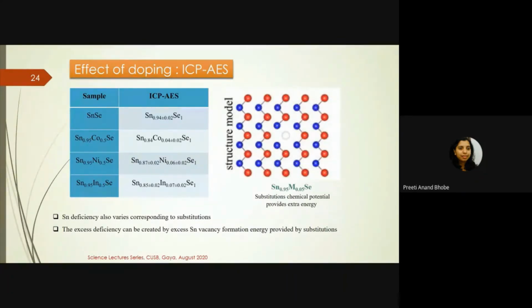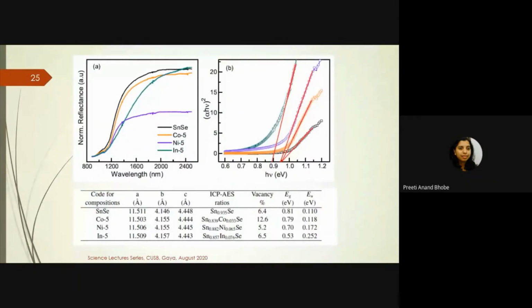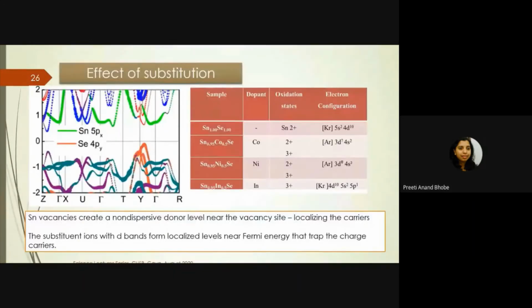What happens to the electrical conductivity? Well, even your gap is getting affected because of these defects. Your optical gap, if you try to do a normal UV-visible reflectance, you find that the absorption coefficient is drastically changing, or there is variation in the gap values. The energy of the gap is changing, it is decreasing. What it all tells us is that when you put elements like cobalt and nickel in this material, these are basically d bands, highly directional d bands, and they add to the band structure of SnSe, where the Sn states are the green bands here and the Se states are the orange bands shown here, and it's a direct gap semiconductor.